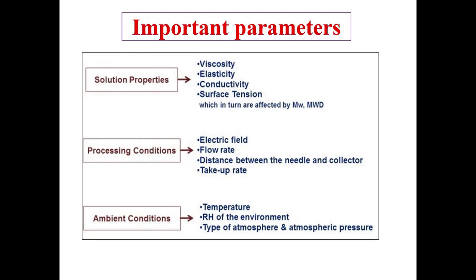Important parameters: solution properties. These are the important parameters for solution properties, such as viscosity. Moderate viscosity is required, and if the viscosity is moderate, elasticity is balanced. Conductivity, surface tension, which in turn are affected by molecular weight and molecular weight distribution.